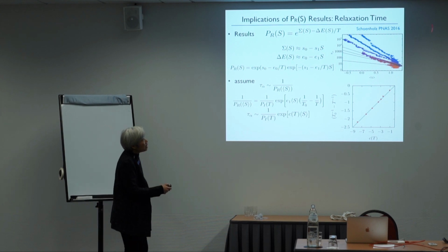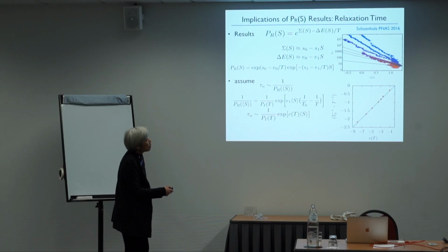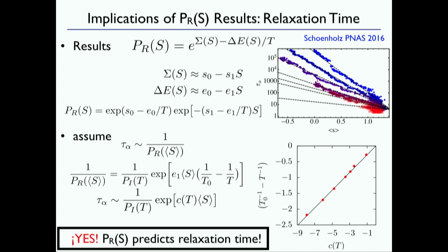And now I can look at the aging systems. In the aging systems, the relaxation time is increasing with time, and the average softness is decreasing. So each aging system is following along a different trajectory, and each trajectory here is for a different temperature that I'm quenching to. And I can pull out the slopes of these lines. It should go like 1 over T0 minus 1 over T. I can plot that. This is what I expect from the expression, and this is what I actually get from the slopes of the lines. It works really well. So this is a very simple picture for the relaxation time as a function of average softness.